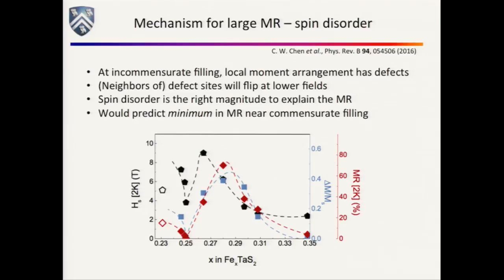So here's what we think is going on. At incommensurate filling, there are going to be some local moments. We know the fluctuations of local moments give you a contribution to the resistivity; you see that just in R versus T. What we think is going on here is that moments at defect sites, or next to defect sites, are going to be easier to flip. They're going to be easier to coerce. So as you ramp up and approach the coercive field, you're going to flip a bunch of those, and you're going to get scattering off of what are now effectively defect sites because of spin orbit effects.